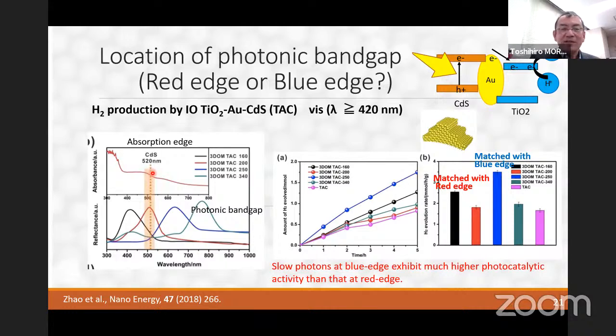In this figure, the blue line depicts the reflectance spectrum of the TAC photocatalyst with a macropore size of 250 nanometers, where the blue edge, this is absorption, this is PBG. That means the blue edge of the photonic band gap matched well with the absorption edge of the cadmium sulfide, okay? This figure shows that the TAC photocatalyst possessed the best hydrogen production.